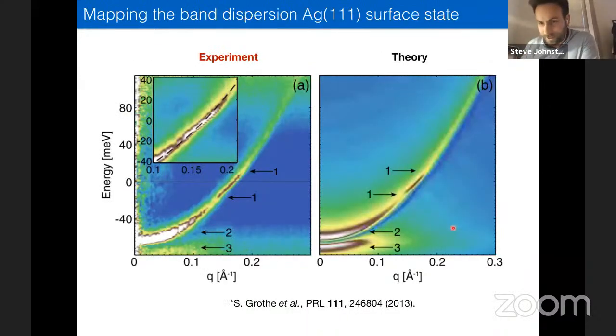And again, just because I like showing it, you can do very detailed simulations. So again, this is comparing to that silver surface state. You can grind through the algebra at various energies, and you can recreate the dispersions this way, and really link the dispersion of this feature back to the actual band structure. I'll just briefly mention these little other arrows I'm indicating. This is actually an electron phonon kink that you normally would only see in ARPES. And this little state that you're seeing here happens to come from the fact that these are unitary scatterers, not Born scattering. But the point is that using this technique, we can reconstruct what the band structure would look like. We can compare that to experiment.